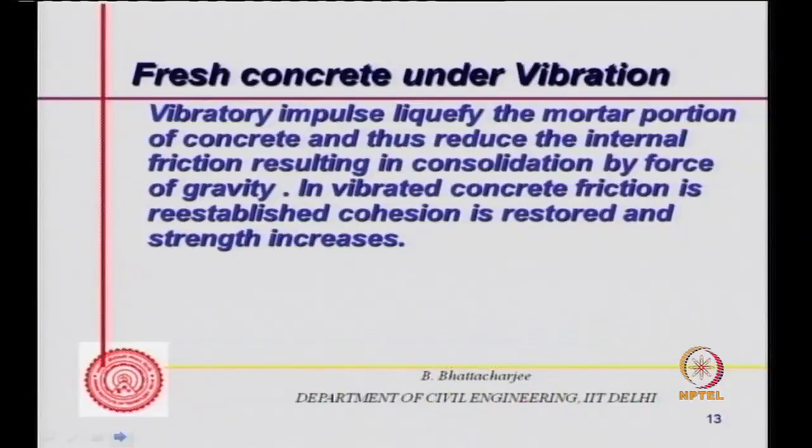So what happens? Vibratory impulse liquefies the mortar portion of concrete and thus reduces the internal friction, resulting in consolidation by force of gravity. Then once the concrete is vibrated completely, the friction is re-established, cohesion is restored and strength increases. Now, how does it occur?